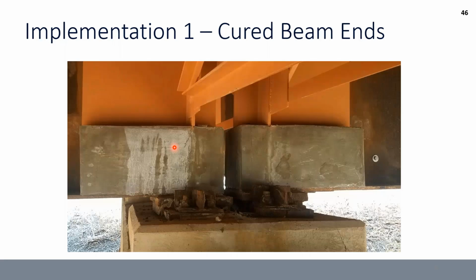And here's an example of those cured beam ends, just following the state of Connecticut procedures. They also painted above the UHPC in that region, and that's kind of standard practice for weathering steel that they implemented. Another thing I'd like to note is just that hole that was left in the web that they went back and filled with, I'm not sure if it was either stainless steel or galvanized, but a corrosion protected bolt.